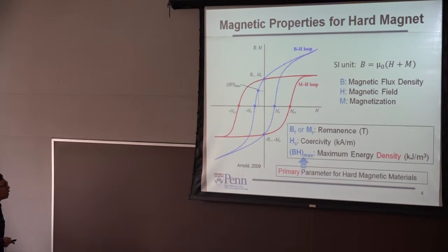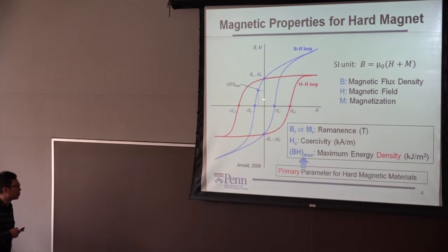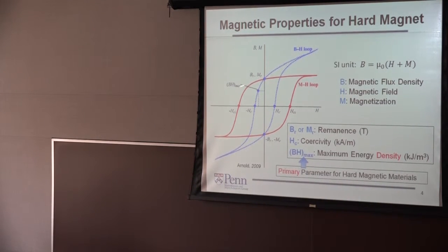Before I go to the main part, I will give you a quick refresher on a few magnetic properties that are important, especially for permanent magnets or hard magnets. The remanence and coercivity are defined by the hysteresis loop, the intersects of the hysteresis loop with the B axis and H axis. Both of these parameters can be captured in one single parameter, the BH max. It's defined as the maximum rectangular area underneath the BH loop in the second quadrant. And this is one of the primary parameters for characterizing hard magnetic materials.